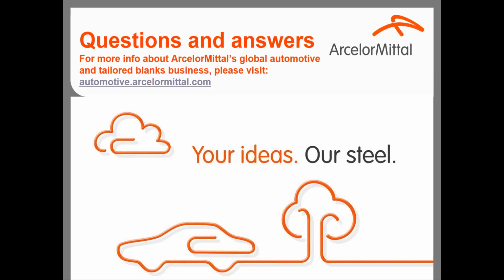That's a great question. It's a very specific question relating to our hot stamp laser welded blanks. For those of our customers who are currently designing with the hot stamp laser welded blanks, we have to do a special process for the aluminum silicon coated laser welded blanks where we remove the coating locally before welding, and that's because the aluminum, if that gets into the weld pool, leads to contamination of the weld seam, and so we don't get recovery of good properties.